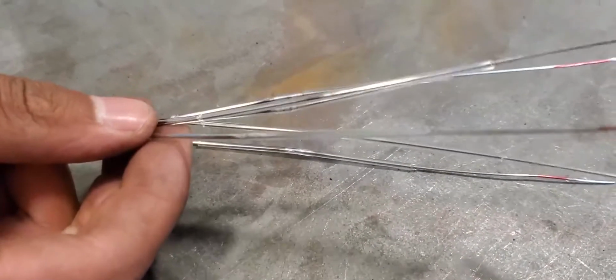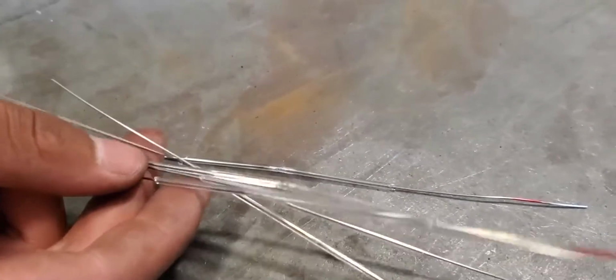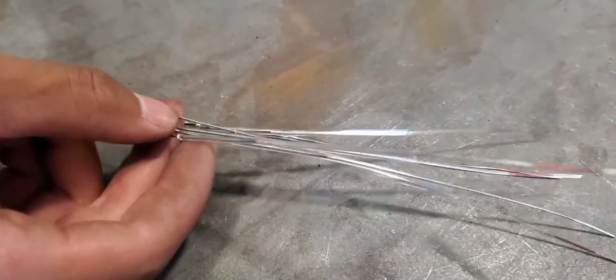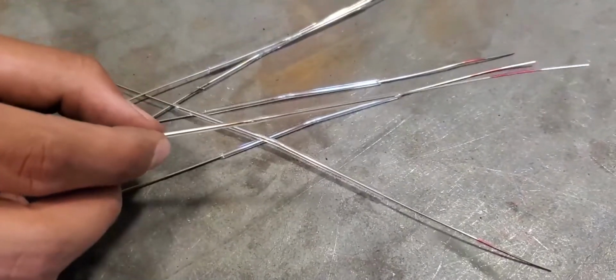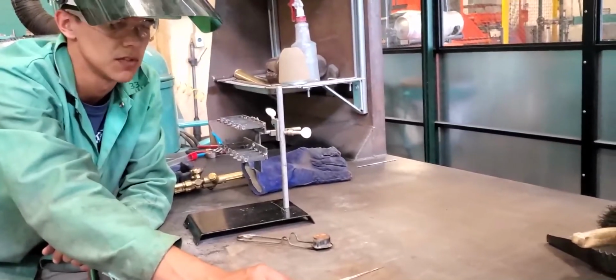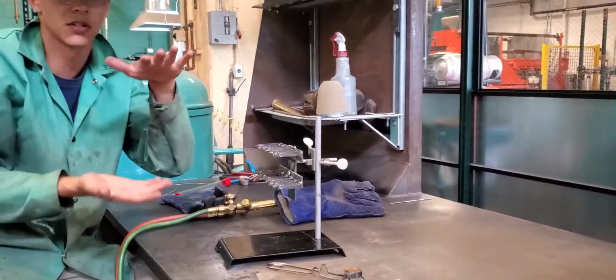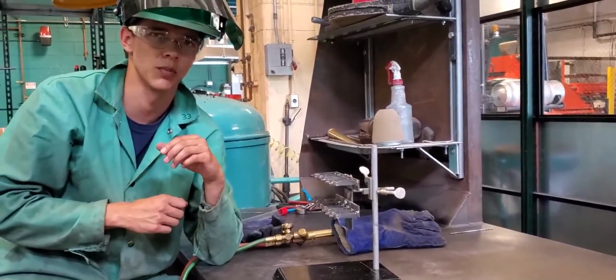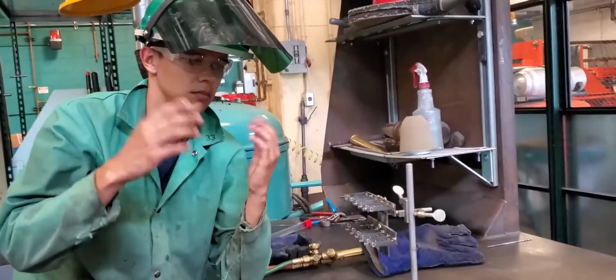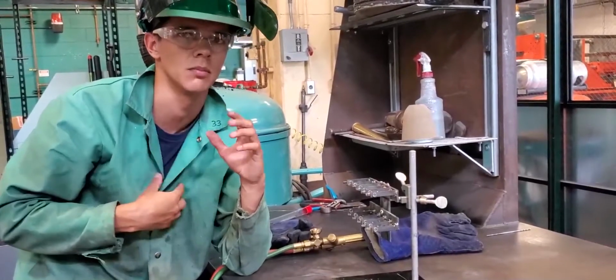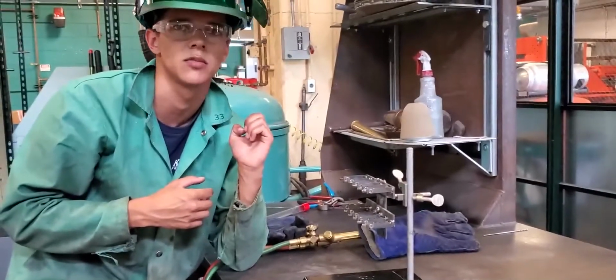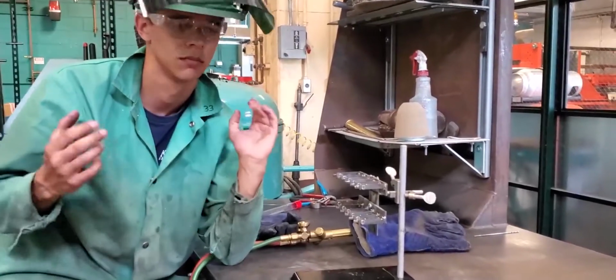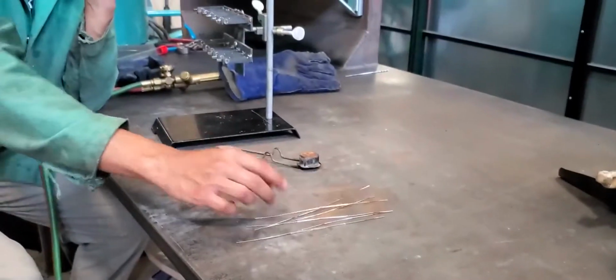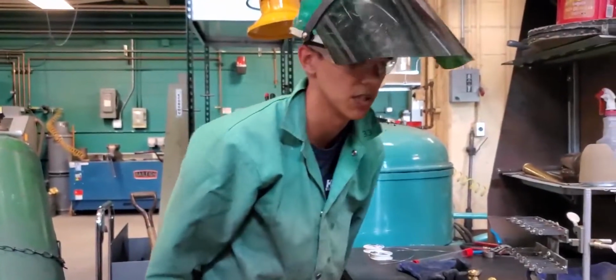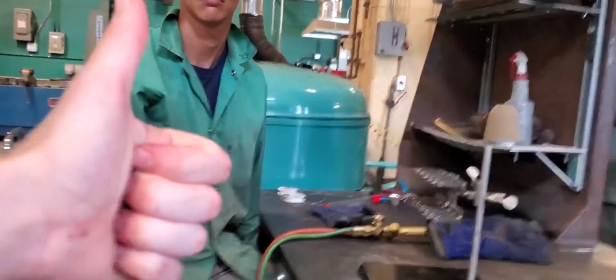Usually it's not as good. Usually you'll get one or two that fail. It's just a matter of tweaking your method of melting the junction. I found that you should only apply heat until it's molten and then quickly release. The longer you hold it and try to make the junction bigger, it just seems to crack the quartz more often, and then in some cases it might form like pores in there. So less heat seems to be better, and then just doing an anneal pass to remove any residual stresses so it doesn't bend as much when you're making them. This should be it.